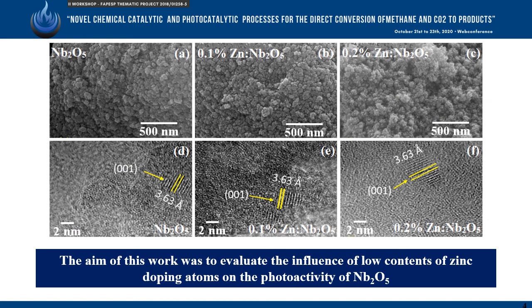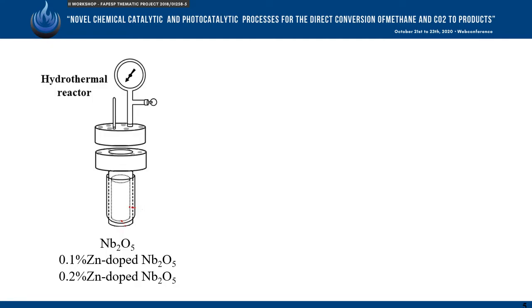Zinc atoms can be a good candidate as a doping element, since it presents an ionic radius and electronegativity similar to that of niobium. In this sense, the aim of this work was to evaluate the influence of low contents of zinc doping atoms on the photoactivity of niobium pentoxide photocatalysts. The undoped and zinc-doped niobium pentoxide photocatalysts were synthesized by the hydrogen peroxide method followed by crystallization under hydrothermal conditions. Low contents of zinc such as 0.1% and 0.2% were used.